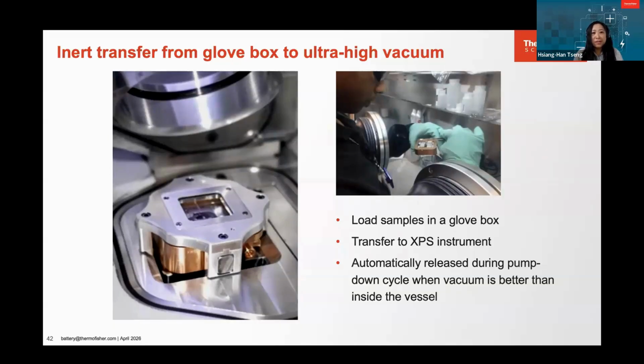On some of our systems, we can use Clean Connect, but there's also an alternative, which is a vacuum transfer module. It's essentially a special sample holder that allows you to load your sample under a lower vacuum. Once it's loaded, you put it in the system and it will open again when it's pumping down. On this slide, you can see the version of the sample holder that we use for our K-Alpha, Nexsa, as well as HyPulse systems.